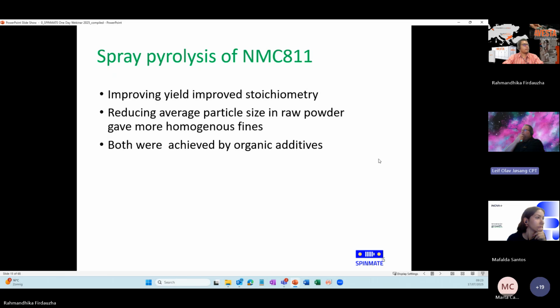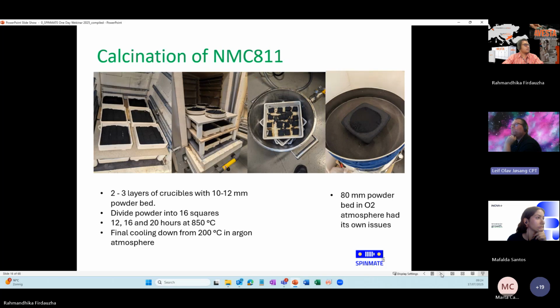We also found that we have lithium loss. This was a lot less surprising, and we coped with that by doing a small-scale test with different amounts of excess lithium, and we landed on 10% lithium excess for the upscaling process. Move on to the next one.